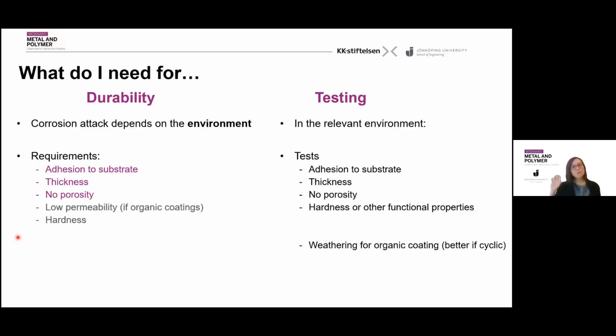So when you plan testing to check the quality of the choice you made, remember two important things. One, check them and do the testing in the relevant environment, since different environments contain different aggressive elements. And test these requirements—adhesion, thickness, and defects—more than the performance of the coating itself. Therefore, you have to test real components.